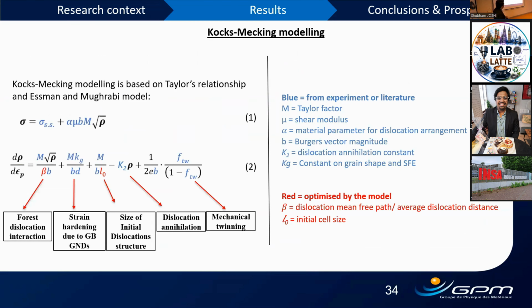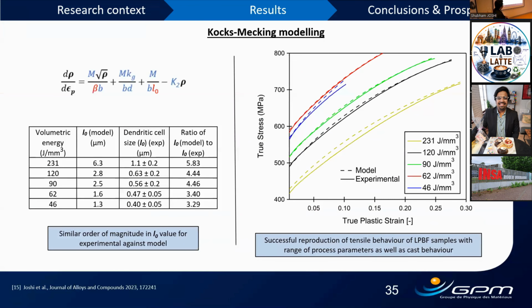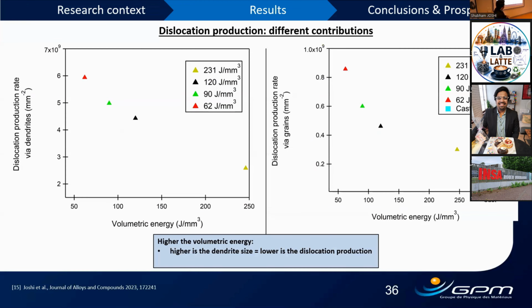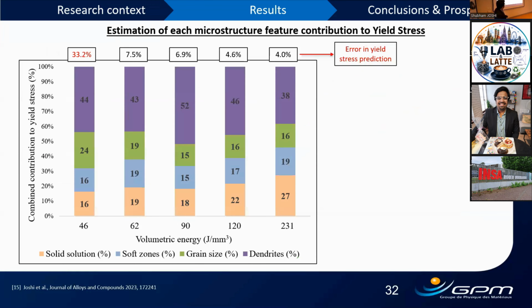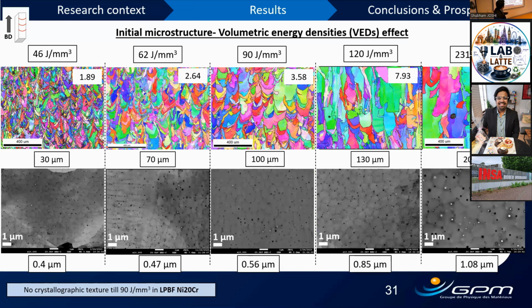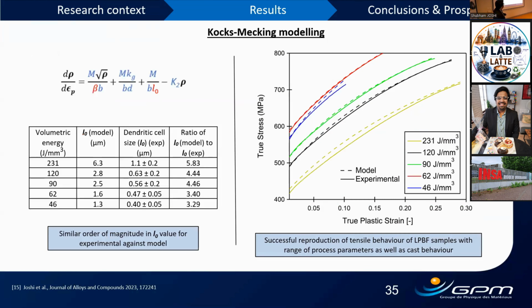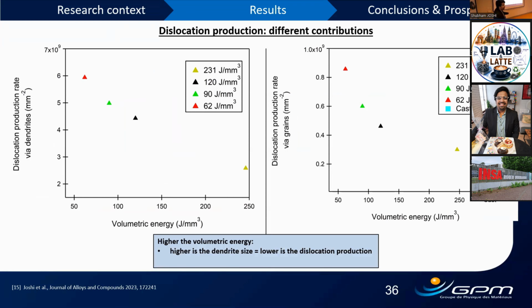So in strain hardening modeling, we see that for the dislocation production mechanisms, when we change the VED from 62 to 120, it's a huge change. If you remember this slide, we changed from 62 to 120, so we have almost double the VED. So the error will be significantly smaller than the change that we have here, but still we see the dislocation production mechanisms, for example, are of the same order of magnitude. So it will not change significantly. The physics interpretation will be there, what we are showing here.